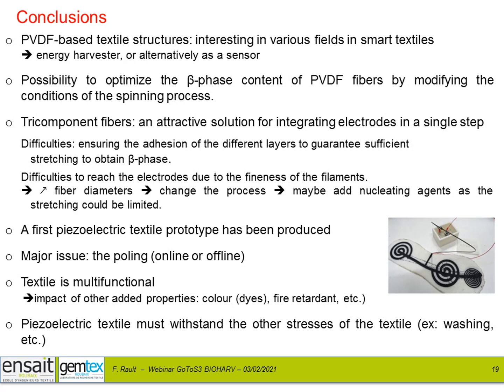We succeeded in producing a first demonstrator to validate our concept of PVDF textile harvester. To optimize the piezoelectric response of PVDF textile, the poling is one of the main issues to overcome. There are different alternatives. This poling could be made online or offline. In terms of perspectives, since textile is a complex material, it is necessary that piezoelectric textile structures become multifunctional and reach all the usual requirements.